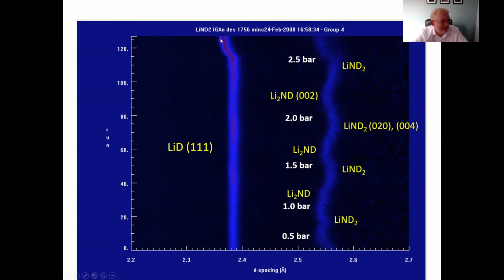And if you look very carefully over at the lithium deuteride line over here, you should be able to see the intensity, which is given by the amount of red in this line, increases, then decreases, increases and decreases, depending on how much gas we're putting onto the system. And we can follow all of that dynamically in a single experiment. Now, we've done it with lithium amide and lithium imide because it's the system we're working on at the time, but it can be done with any system where you have this reversible gas absorption, gas desorption process.